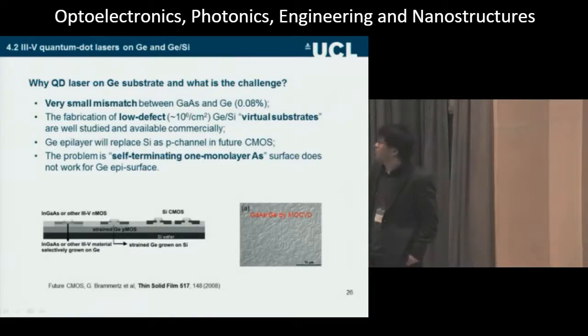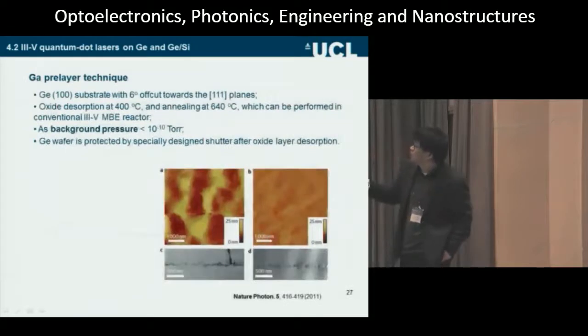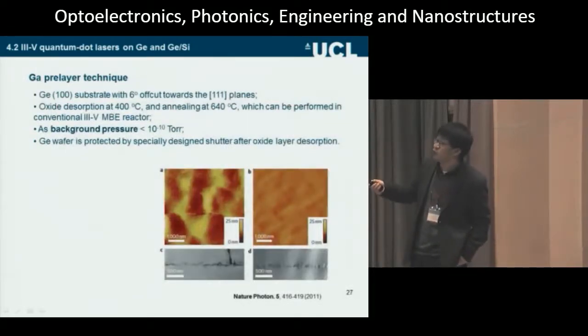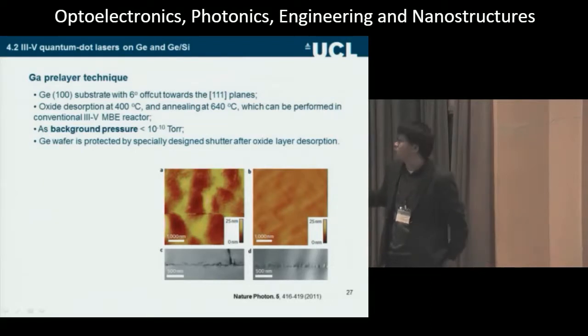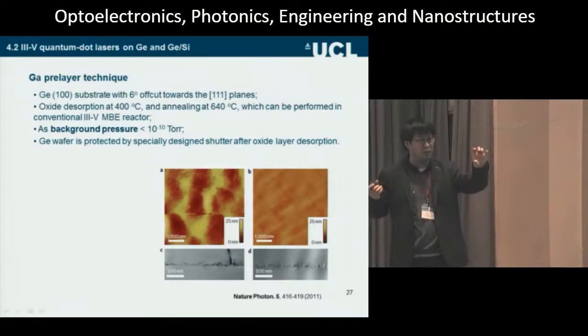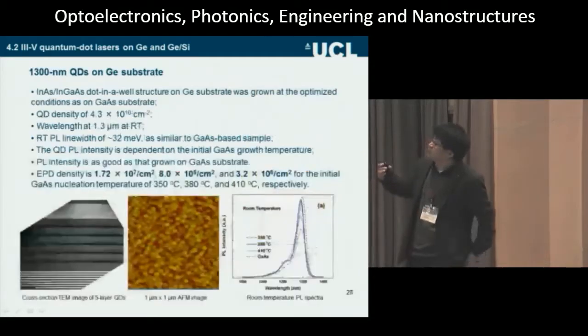When you first do the growth, you can see we use the arsenic pre-layer, the surface is very rough, like mountains at nanometer scale. And also you have antiphase domain formation in the interface that goes to the top. So what we do is use a gallium pre-layer, and you grow the first layer of gallium on the surface, stop the arsenic, go to germanium. You get a very flat surface. You do have some interface defects, but because the mismatch is small, if you grow very thick, you will have relaxation. After that, things get easier.